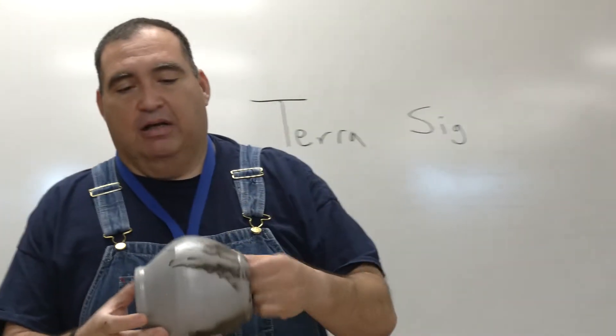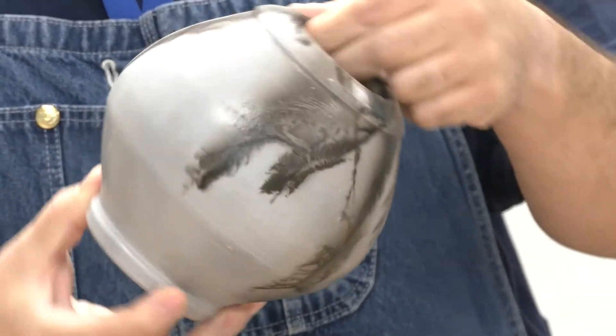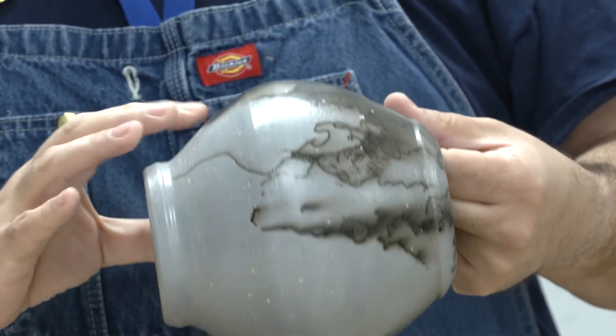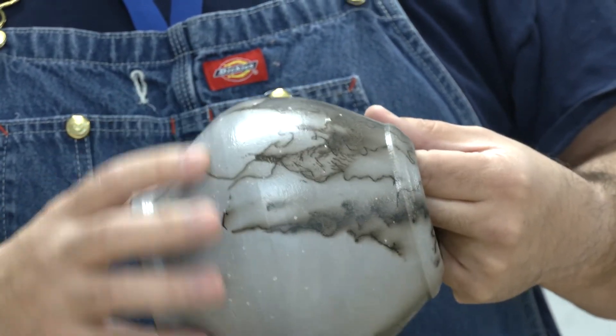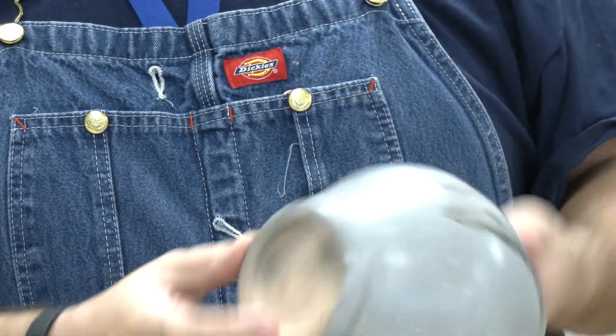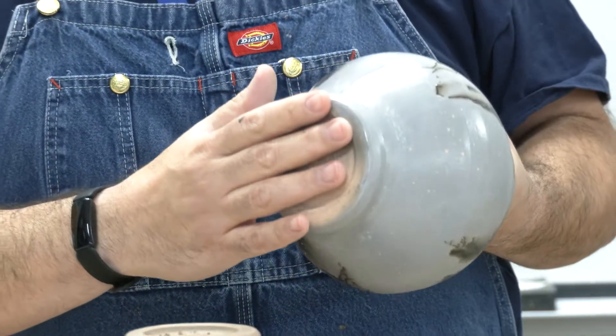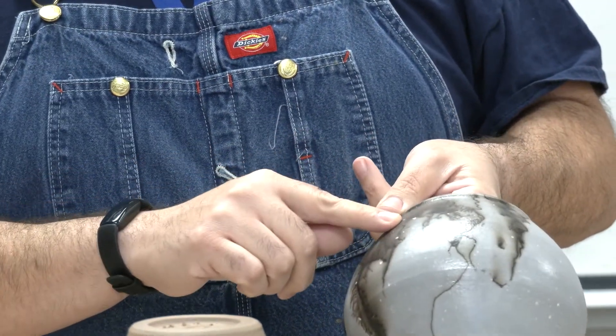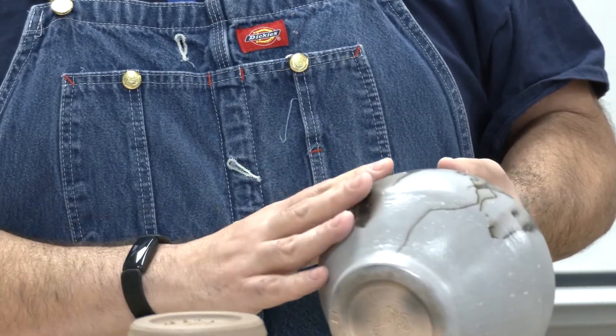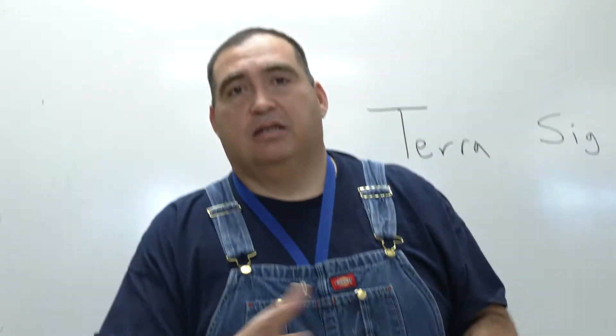This piece actually — if you look at it, you can see the little speckles. This started peeling; it was okay until I drove today and it peeled in the car because I might have needed to wrap it up. Surfaces are usually really fragile, so it's real easy for this to happen. I'm also testing clay bodies, testing the slip to the clay body for proper fit. The thicker the sigillata, the more chance of it peeling, so this sigillata might have been put on too thick.